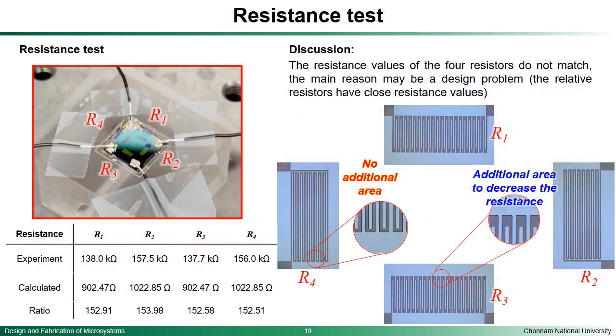After assembling our final device, we tested our resistance. Here we have 4 resistors in our sensor, R1 to R4. We tested the initial resistance values of the resistors, and the data is shown here. We can see that R1 and R3 have lower resistance, while R2 and R4 have higher resistance, but the resistance values of R1 and R3 are close, and R2 and R4 are close. The Wheatstone bridge requires balanced resistance values, which means the 4 resistance values should be close. That would be better. But actually we made a mistake here, because when I designed the mask, the